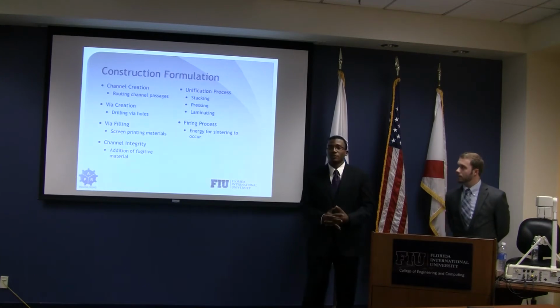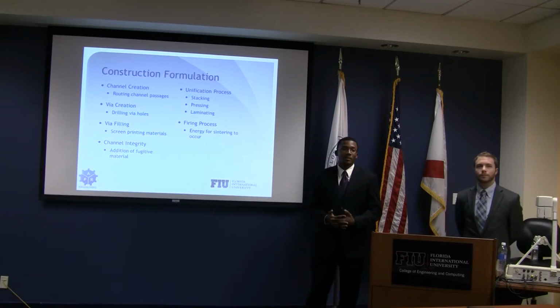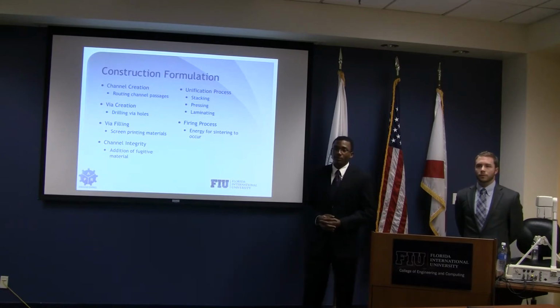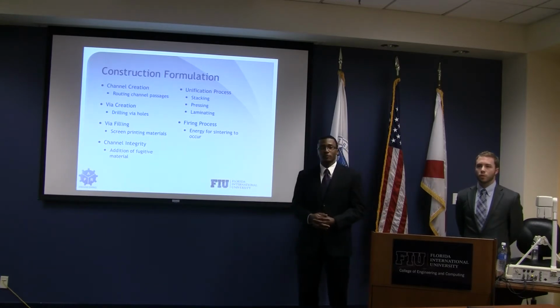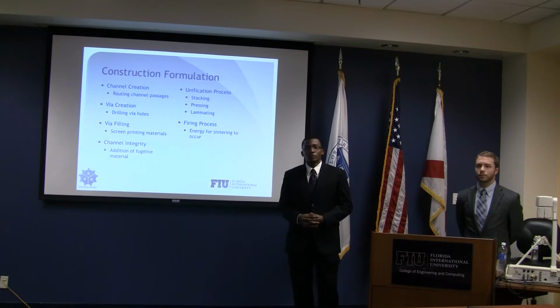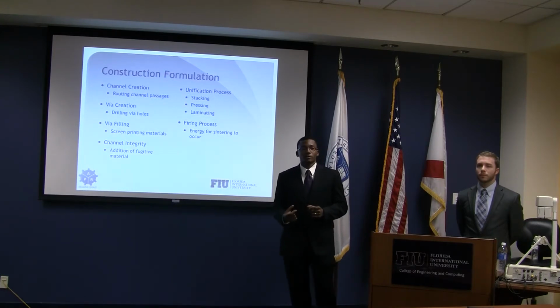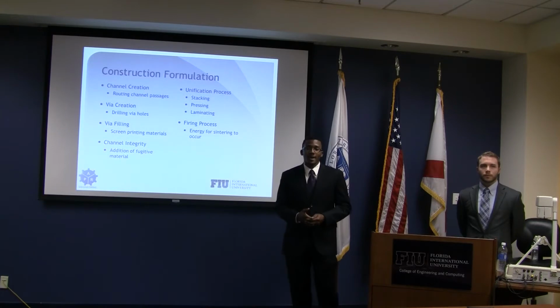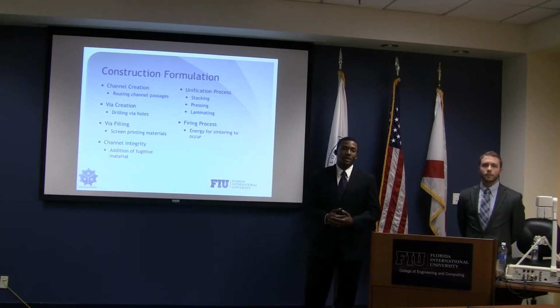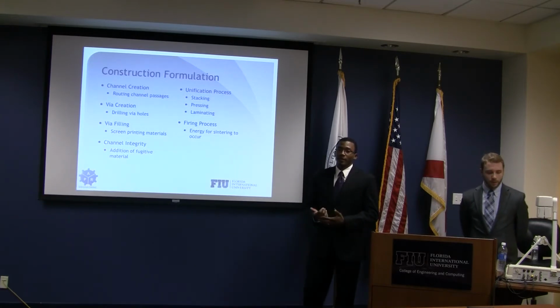So the construction process begins with stacking and laminating ceramic tapes using a heated manual press. We then drill microchannels and pinholes through the surface of the body, and afterwards we fill the channels with fugitive material in order to ensure that the structural integrity of the microchannels is maintained during lamination and firing. The pinholes are filled with silver paste, and afterwards the entire device is laminated once more before finally being fired for sintering.